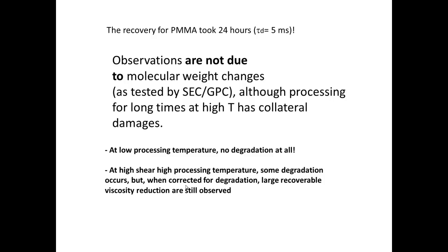So we know that when there are molecular weight changes, we know how to correct it. This is what I say in the last paragraph. At high shear, high processing temperature, some degradation occurs, which can be intense for some polymers, for instance polyolefins. But when corrected for degradation, large recoverable viscosity reductions are still observed. So this has nothing to do with topological changes, although topological changes may occur, do occur, and influence the results, sometimes overshadowing the results that we want to obtain.